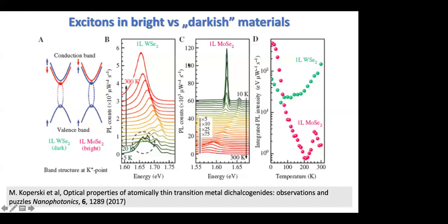Okay, so if we look at the temperature dependence of luminescence from molybdenum diselenide, the bright material, by increasing temperature, you start to populate thermally more and more dark excitons, which means that the intensity decreases as a function of temperature, except for this part of the highest energies, which is related to another effect.